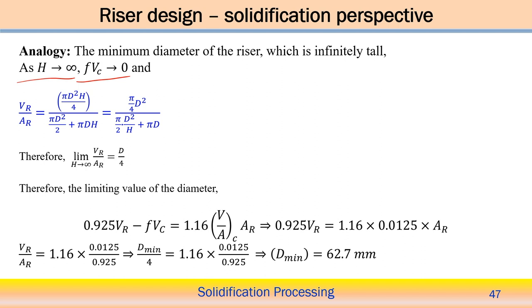If this is the case, we can go back to the volume by area ratio. For this case we can calculate it as pi d square h by pi d h, and divided by h, so it becomes d by 4. So the limiting VR by AR, if h tends to infinity, becomes d by 4. Therefore the limiting value of the diameter can also be found, assuming that VR by AR equals d by 4.